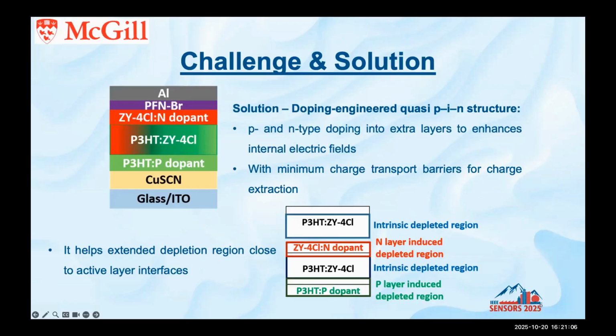To explain how this happens, in a conventional device we have a depleted region around the active layer when we have only a mixture, or bulk heterojunction. When we add two more layers, the N layer and P layer, at the junction of these two layers some kind of depletion also happens. So besides the intrinsic depletion region that we get for the bulk heterojunction, we add two artificial depleted regions that can increase the overall depleted region area, and it helps us to fully cover the size of the active region.